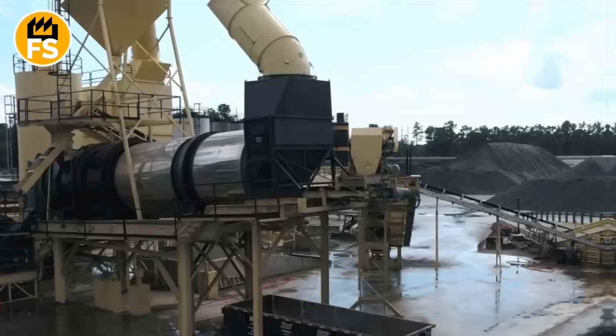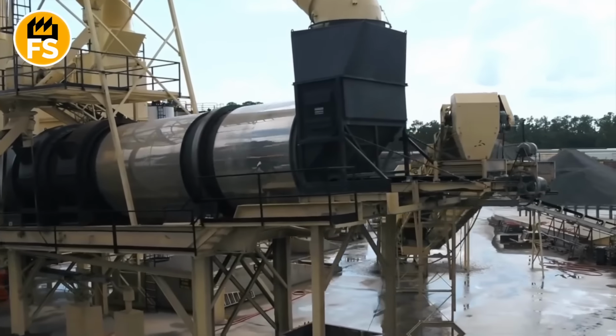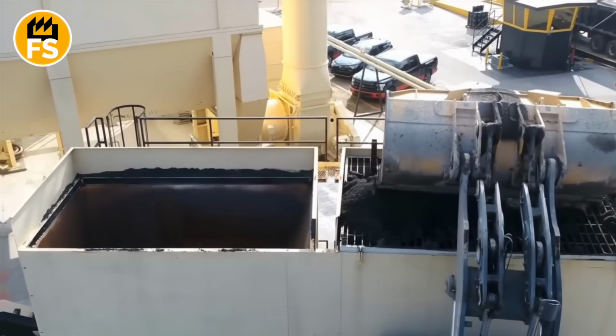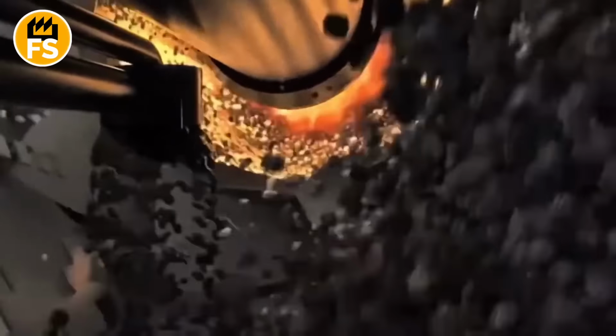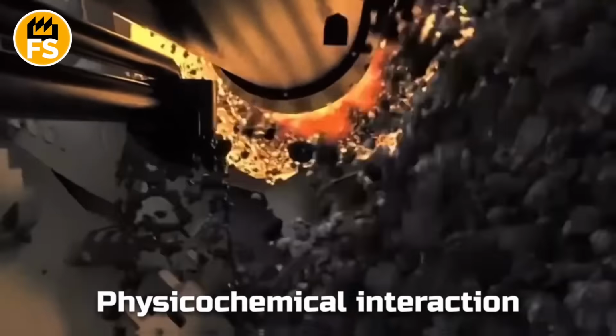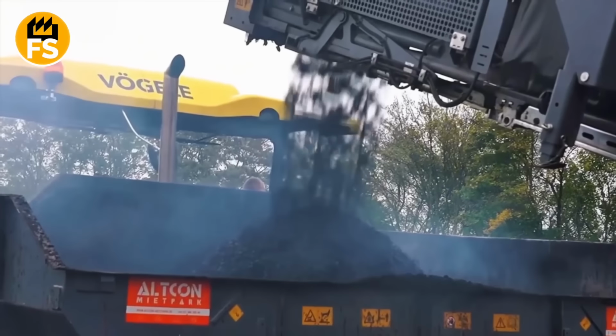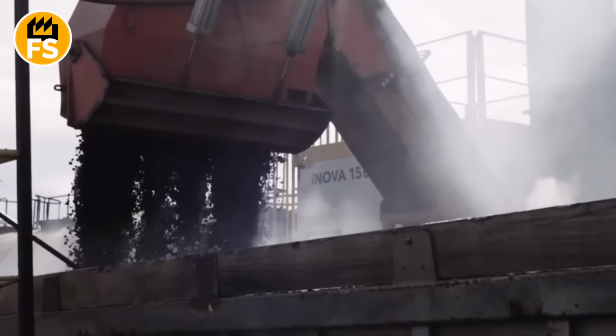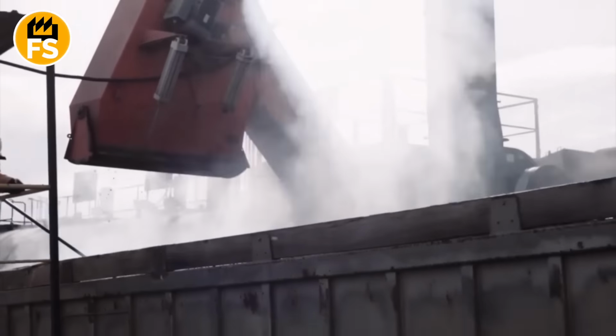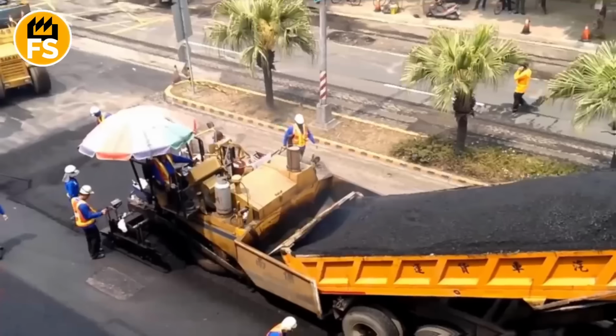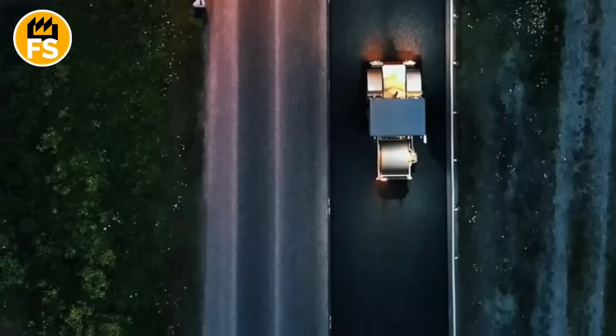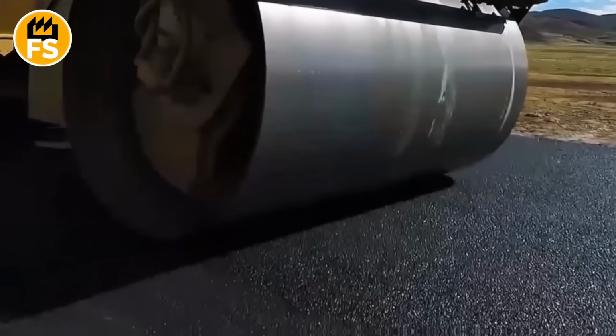During mixing, the rubber crumb particles absorb the lighter fractions of bitumen and swell. This isn't just mechanical stirring, it's a physico-chemical interaction that transforms the binder's properties. The mixture becomes more viscous and elastic, handling temperature swings and traffic loads way better. Mixes run for a set amount of time to hit that uniformity sweet spot, and then the rubber bitumen blend is ready to roll or store temporarily.